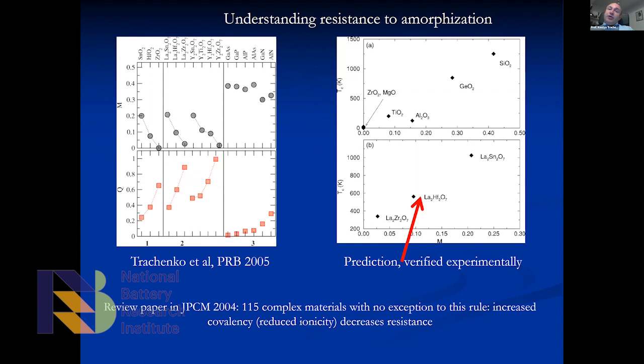Right, so I forgot, it's called a Mulliken overlap population, right? So it's something that quantifies covalency. We can also quantify something which is called ionicity, and this number Q here is the number of charge in the Voronoi polyhedra. So you can actually see to what extent the material is ionic by calculating this parameter Q.